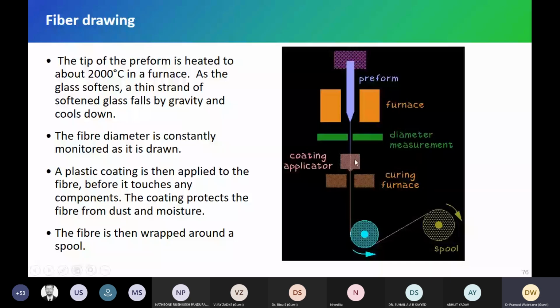So this monomer is here, and when this glass fiber passes through it, it gets coated with that monomer. Then when it comes here, UV ultraviolet rays are kept in this furnace. When it passes through this UV chamber, because of UV, that monomer converts into polymer, and we get the plastic. That is the coating over the glass rod, and we get the optical fiber here. We collect it here in the spool.